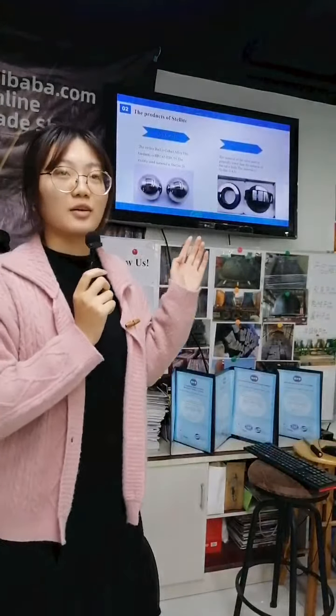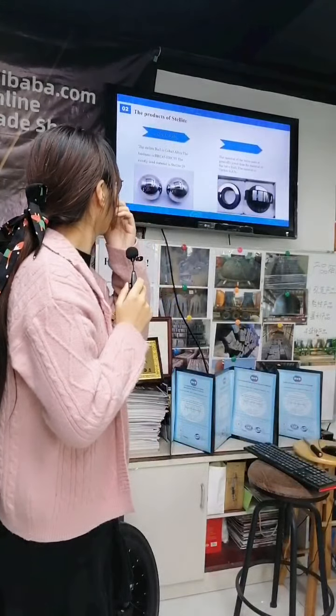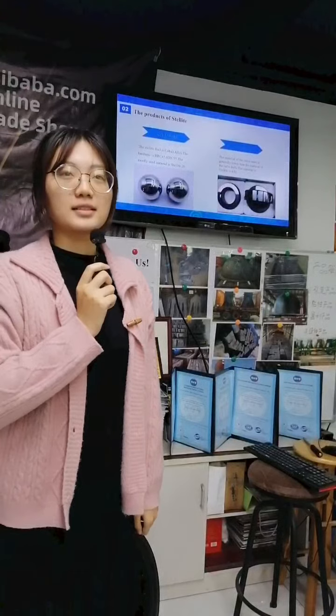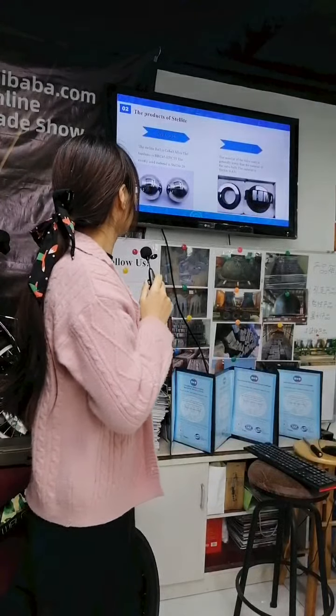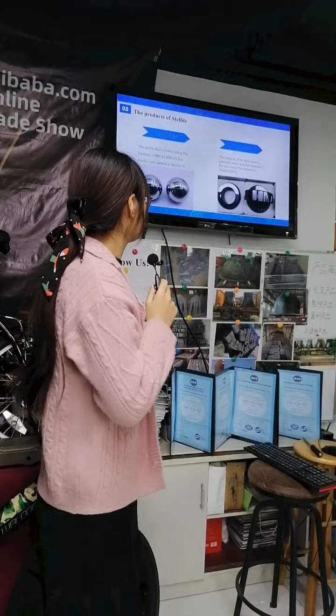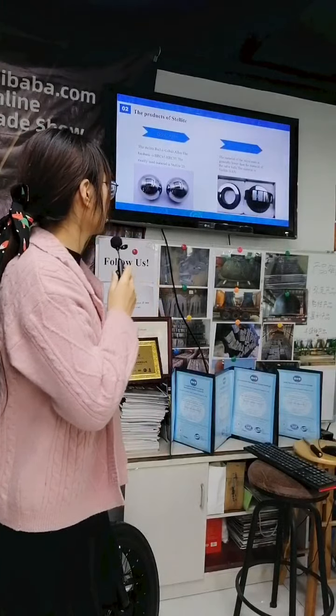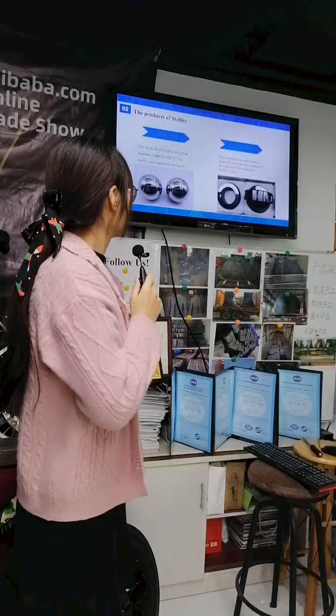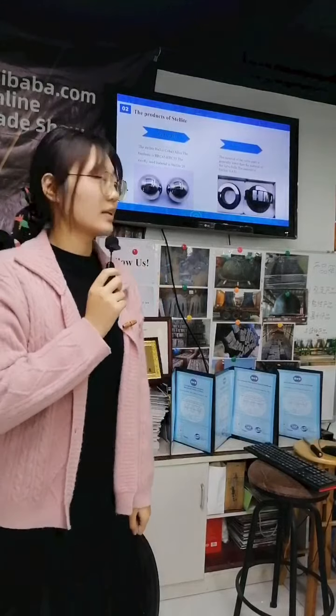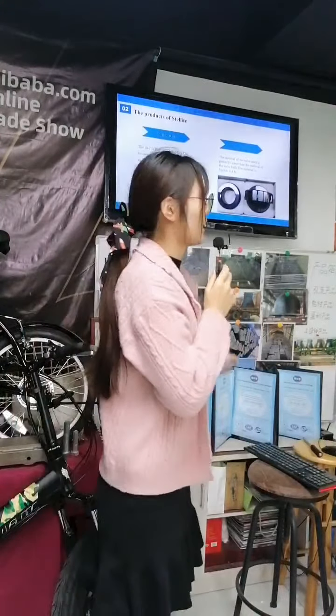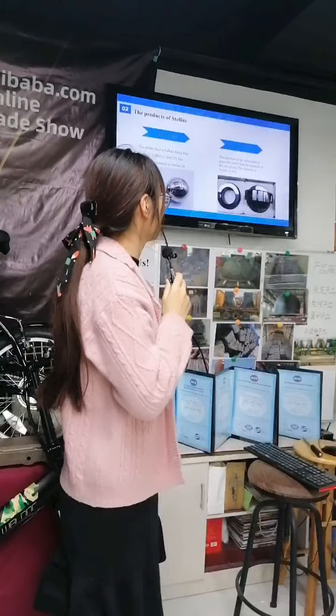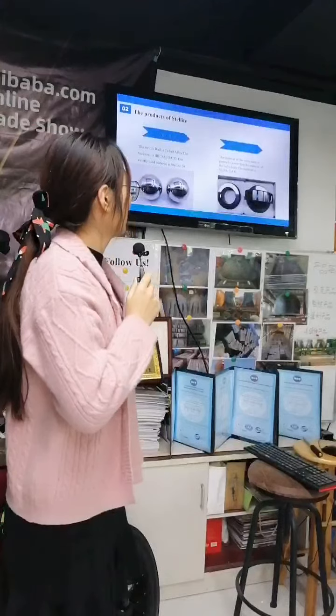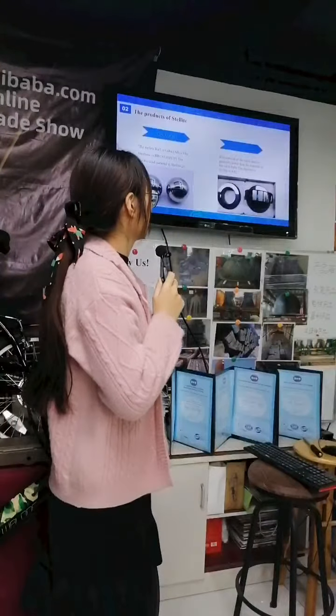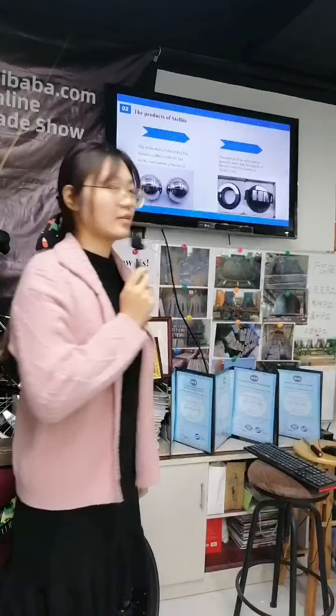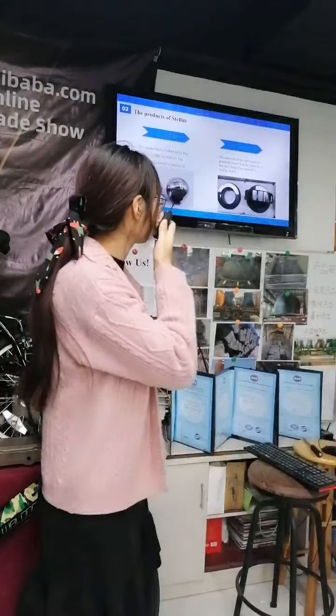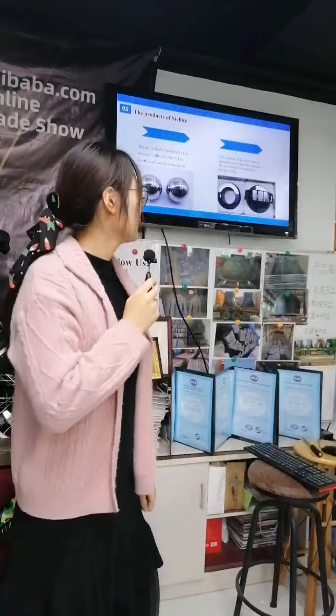And this is a product of stellite. The first picture shows us the stellite ball. The stellite ball is cobalt alloy. The hardness is HRC 45 to HRC 55. The mostly used material is stellite 20. And the stellite seats. The material of the seats is generally lower than the material of the ball. The material is stellite 3. We also call it A3.